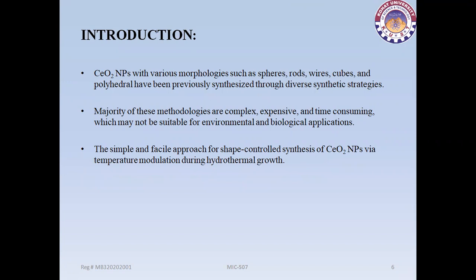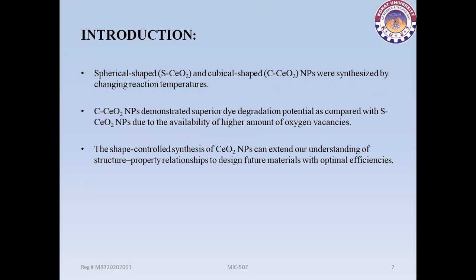synthetic strategies. A majority of these methodologies are complex, expensive, and time consuming, which may not be suitable for environmental and biological application. A simple and facile approach for shape control synthesis of cerium oxide nanoparticle is temperature modulation during hydrothermal growth. A spherical shaped cerium oxide and cubical shaped cerium oxide nanoparticle were synthesized by changing reaction temperature. Cubic cerium oxide nanoparticle demonstrated superior dye degradation potential as compared with spherical cerium oxide nanoparticle due to availability of higher amount of oxygen vacancies.